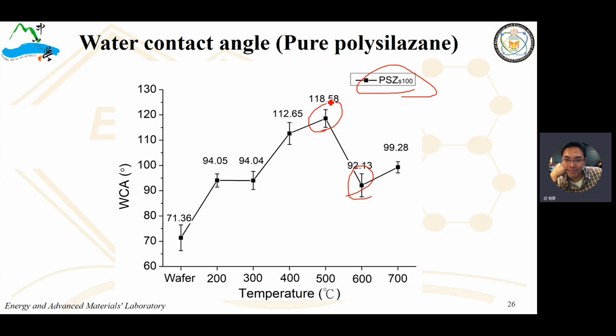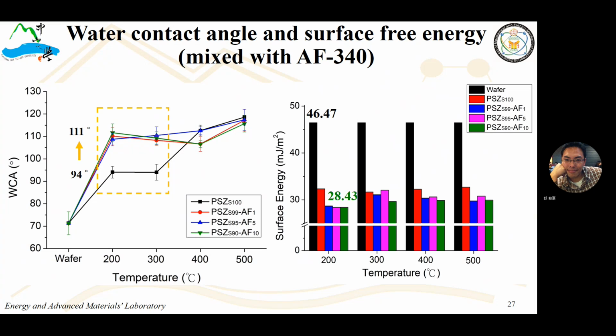Therefore, our experiment will operate below 500 Celsius. And then we can find out that the precursor incorporated with the AF-340 has a contact angle that increases significantly within the temperature range between 200 to 300 Celsius. The contact angle increases from 94 to 111.